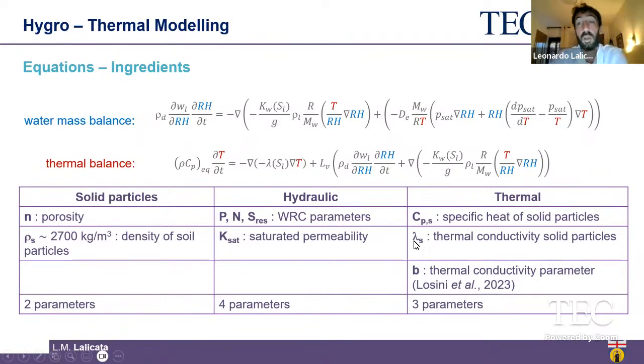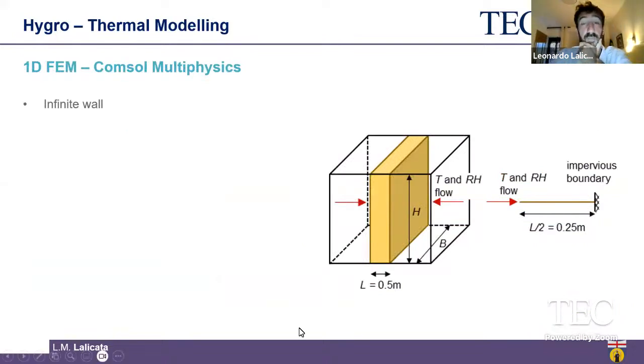And finally, we need to quantify the thermal properties, for which we need three parameters, as I said. So we need the specific heat of the solid particles, the thermal conductivity of the dry soils, and the thermal conductivity parameter, which is the slope of the trend that you have seen before. So with a number of 7, 8, or maybe 9 parameters, we can solve our problem. And now I'm going to show you an example of this hygrothermal coupling. To do that, we started with a very simple model of an infinite wall.